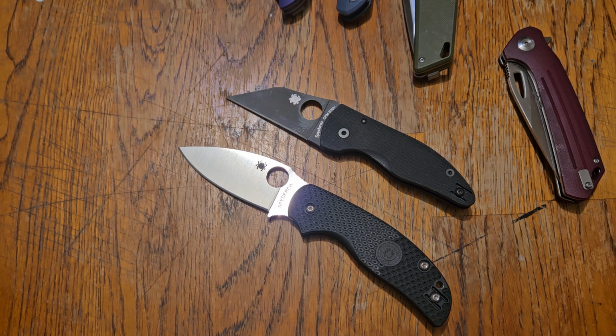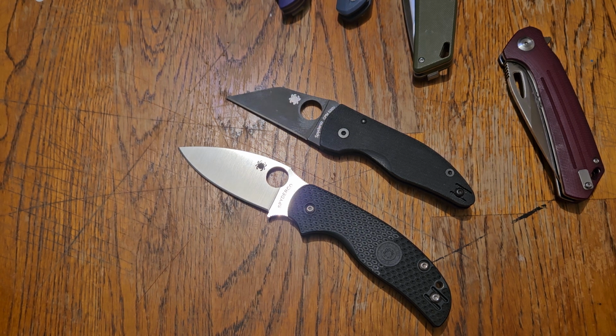And that is because same composition, same geometry. Edge retention is determined by Rockwell. The harder the steel, the longer it's going to cut. This especially holds true in production knives. In custom knives, where you're working with really thin geometries, 5-6 thousandths of an inch behind the edge, super thin hollow grinds, we're not discussing that. It holds true there too, to some extent, mostly, but there are some differences there. But we're talking about production knives. In production knives, it is 100% composition and Rockwell.